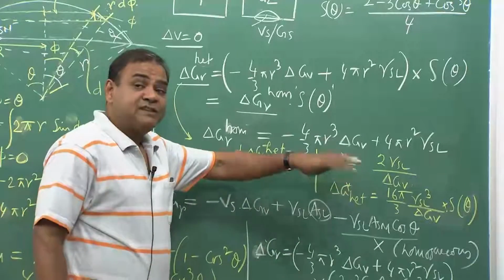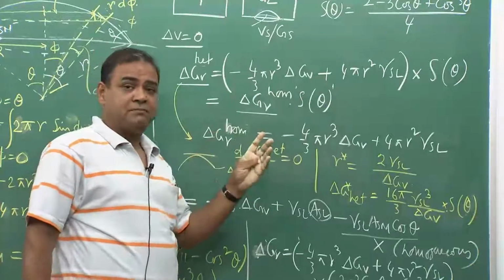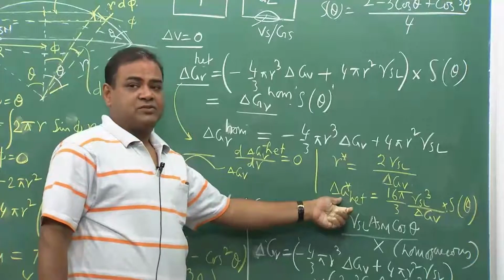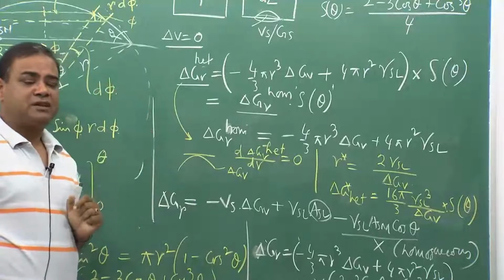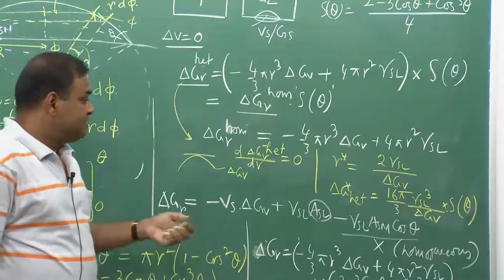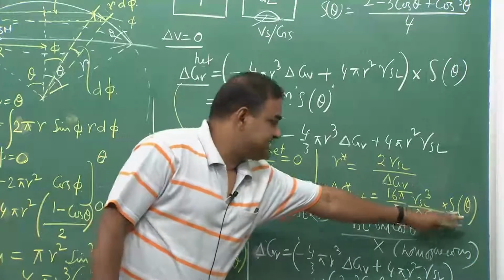The critical r would be the same at a particular temperature below T m, but delta G star heterogeneous, which is the activation barrier for the formation of stable nucleation, is influenced by S theta.